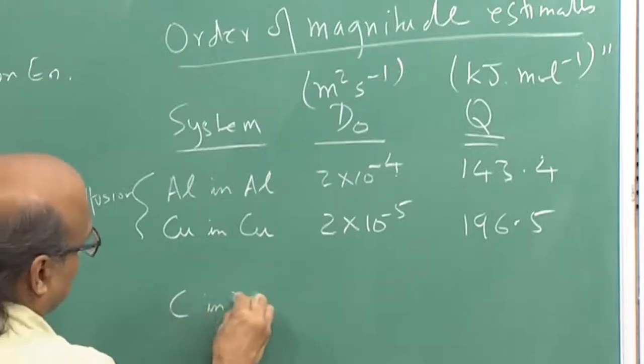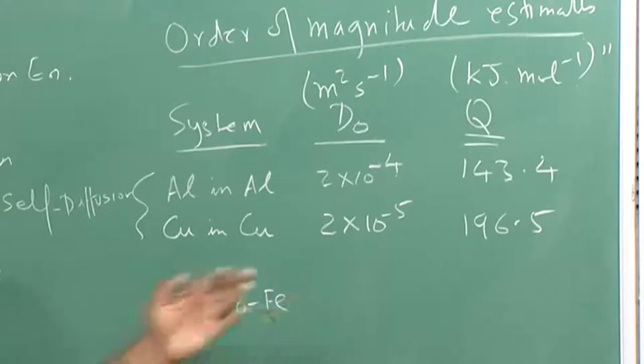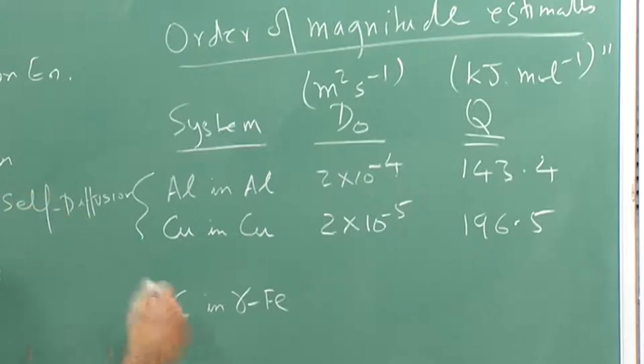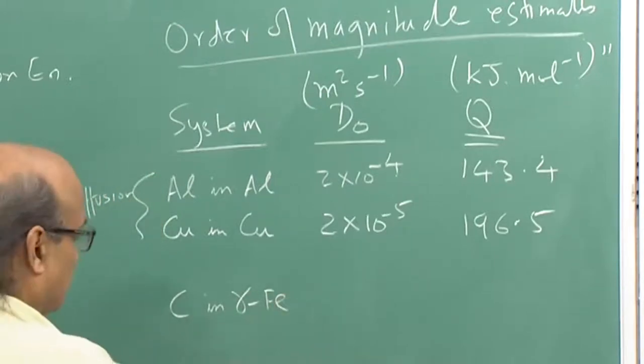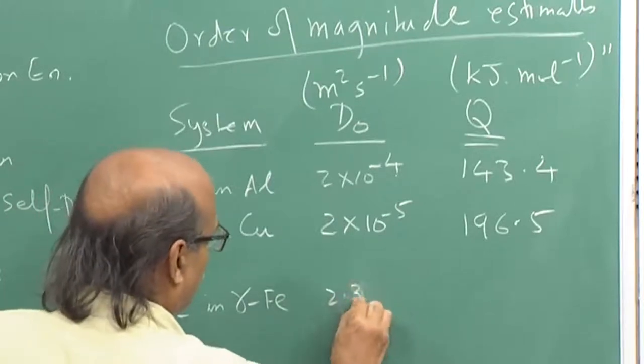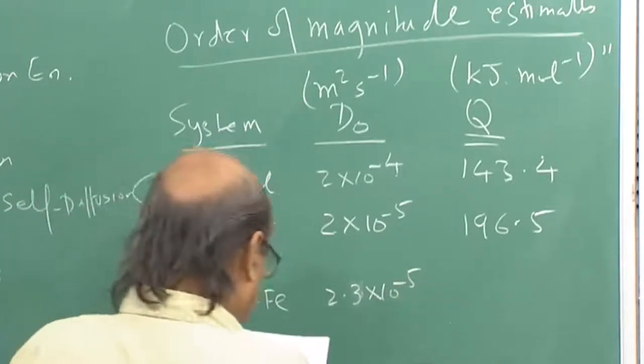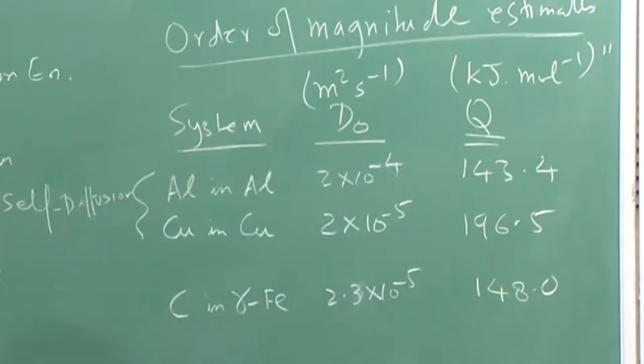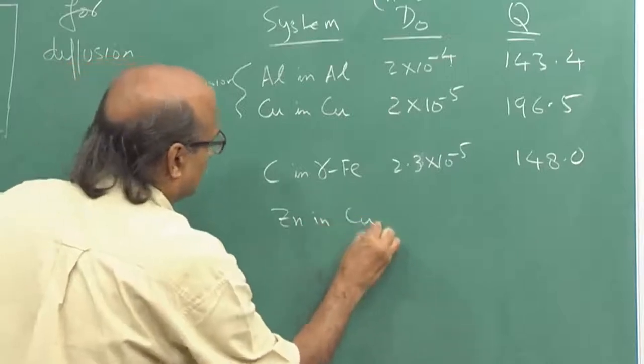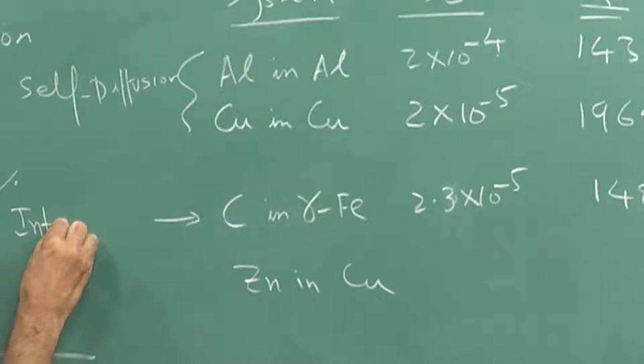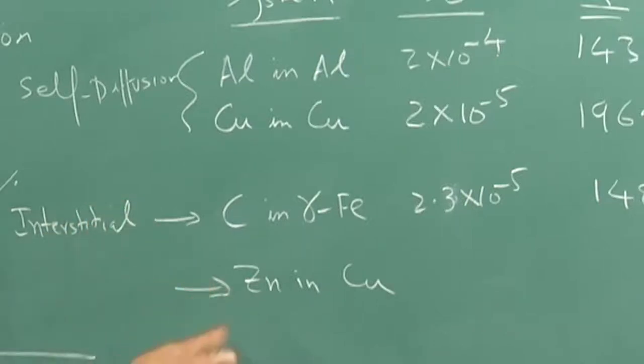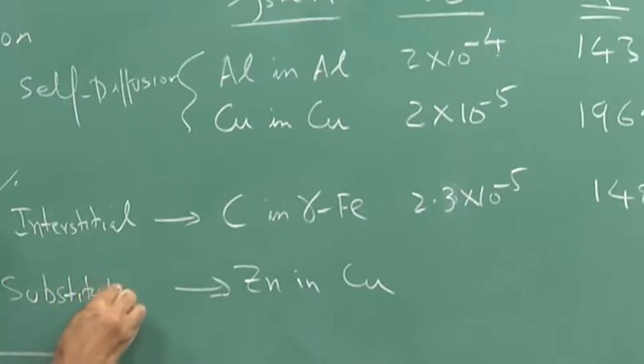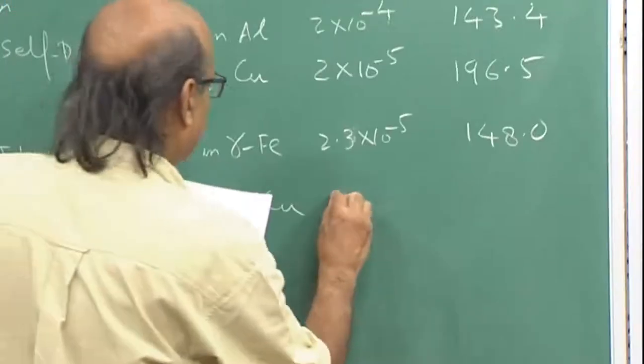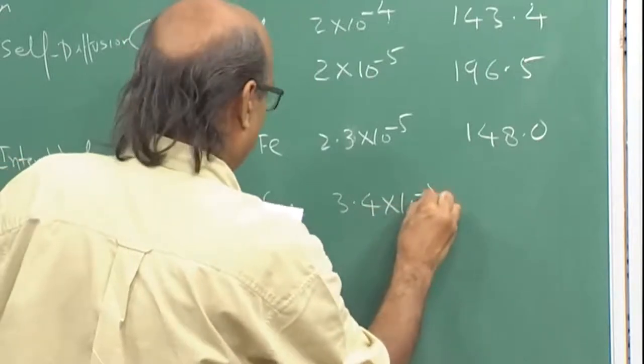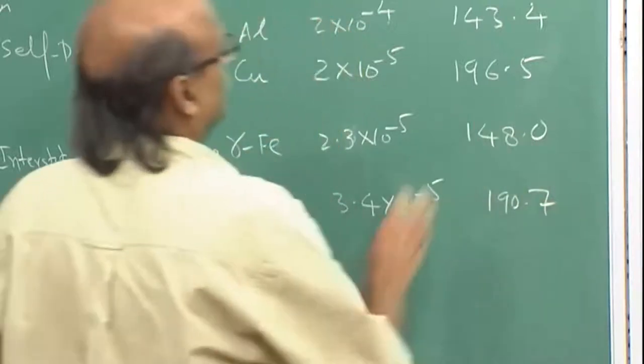Consider carbon in gamma iron, that is, carbon in austenite, a face centered cubic form. Diffusion of carbon in the body centered cubic form of iron would be different from the diffusion of carbon in the austenite form of iron. In this case, I get D0 as 2.3 into 10 to the power minus 5 and Q to be 148 kilojoules per mole. Zinc in copper, now this is the case of substitutional diffusion, whereas the carbon case is interstitial diffusion. For zinc in copper, D0 is 3.4 into 10 to the power minus 5 and Q is 190.7 kilojoules per mole.